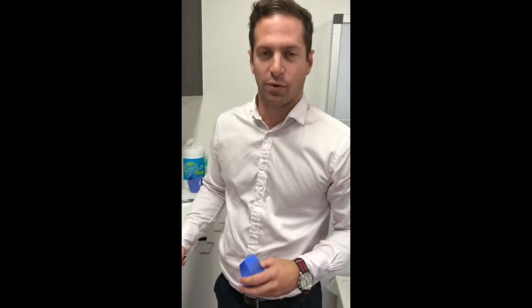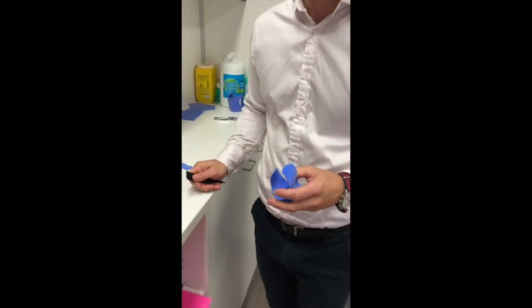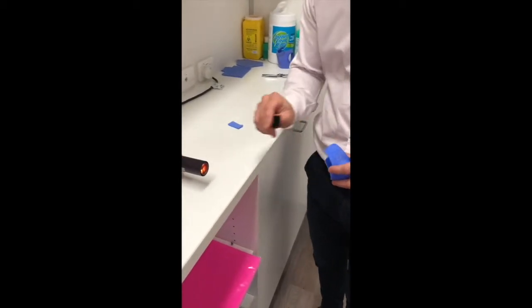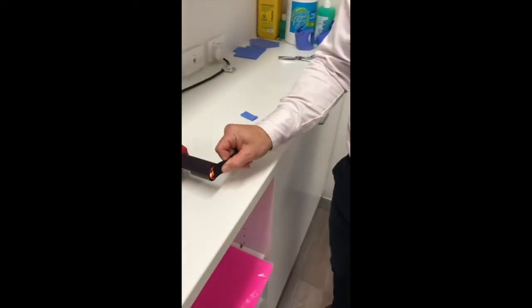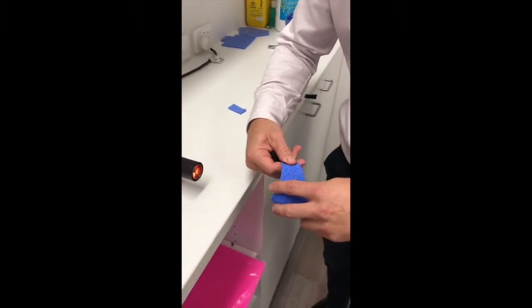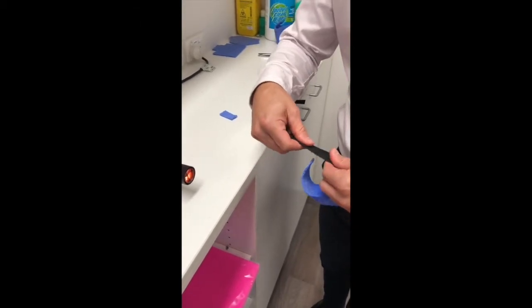We're just finishing off our splint now — we're going to put some straps on. Many of you will have put straps on a thermoplastic splint before, and we do it in a very similar way with one small change. The Velcro loop can be secured directly onto our thermoplastic: three seconds of heat, and then we just press the two edges together to get a nice permanent bond.